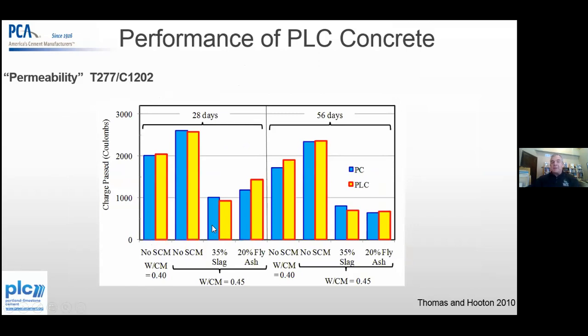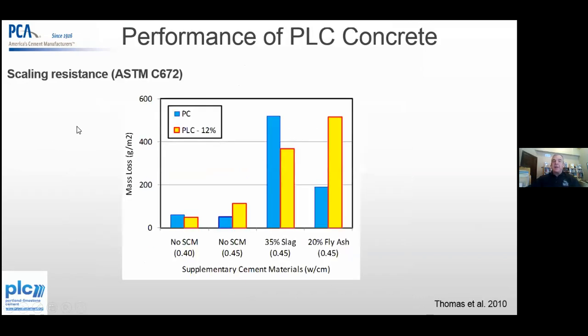So at 28 days, it's comparable at 35% slag below 1,000 coulombs for this test. This is at 0.45 water cement ratio. What was 2,500 coulombs is now below 1,000. And with the 20% fly ash, it's about 1,250 and 1,400 coulombs with the PLC and the PC. At 56 days, it doesn't really drop that dramatically for the non-SCM mix. Water cement ratio obviously plays a part in that, but just by adding in some supplementaries with PLC and with OPC, you get the same thing. You get equal performance and permeability mitigation.